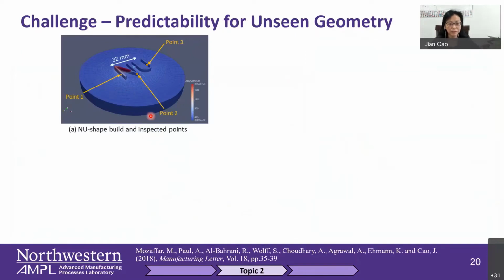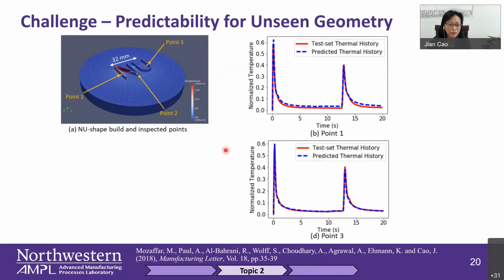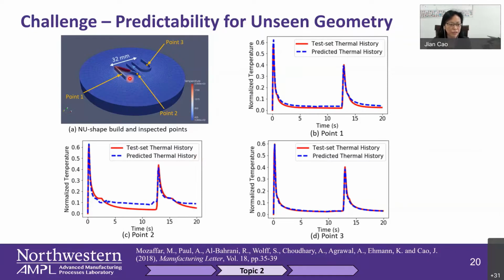Therefore, if you want to make something new, like what we tried to make, the NU shape, and you look at the thermal history at 3 different points, for example, the 2 points, the straight one and the curved one, are predicted pretty well. But the part that we have the N, the transition point, it's not very good. That's because in terms of the training data, we just don't have this kind of complexity, right? So the next step is how do we generalize this to include more general geometry, such that we can predict more general, different builds.